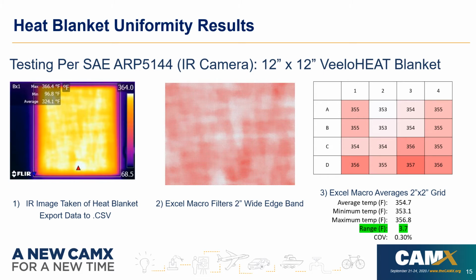Then we would take that CSV file and we have a macro using Excel that we would filter out the 2-inch band around the blanket. Next, we would basically break that filtered image into 2-inch blocks. We would then take an average of each block and report that here on the right in figure 3. And then our macro would average that 2x2 grid and report a temperature range. In this case, we are seeing a range of just under 4 degrees, 3.7 degrees here. That's well within the plus or minus 10 degree requirement for this SAE test method.